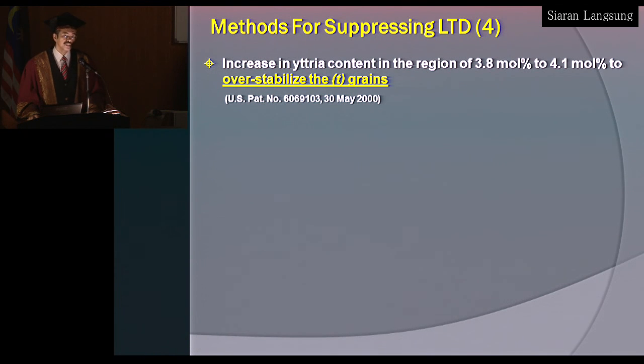By increasing the yttria content to 3.8 or to 4 mole %, the tendency is to overstabilize the tetragonal grain. Again, there's too much stabilizer there. It interrupts the transformation toughening process. For transformation toughening to take place, the tetragonal grain has to be in the metastable form. It cannot be in the stable form. So you should keep the 2.5 to 3 mole % yttria.